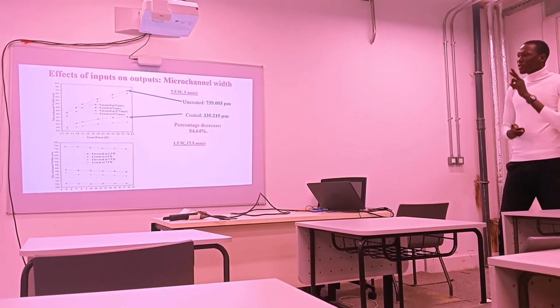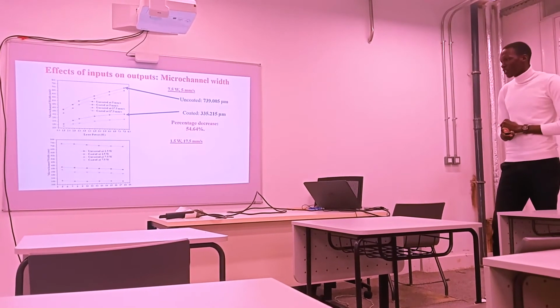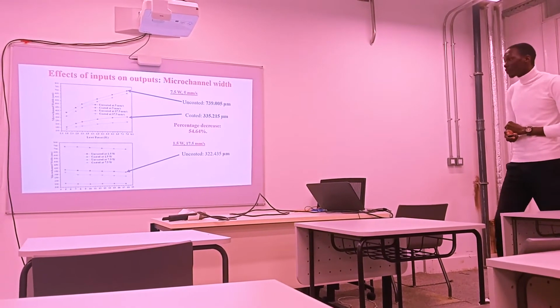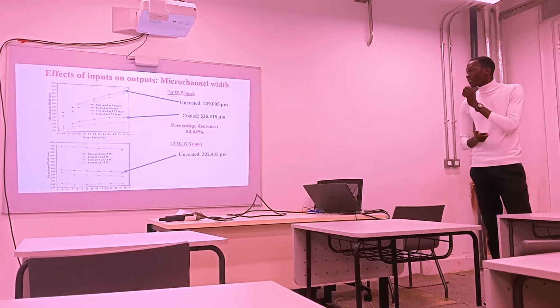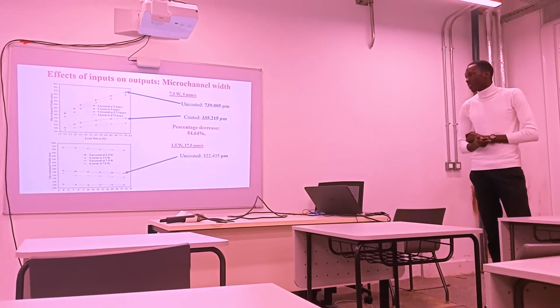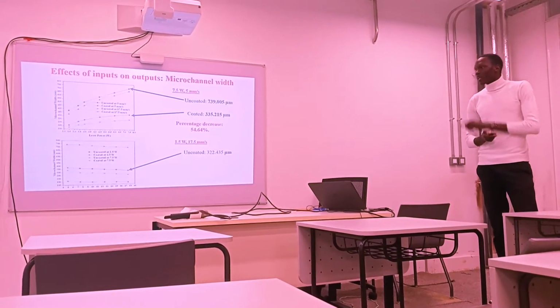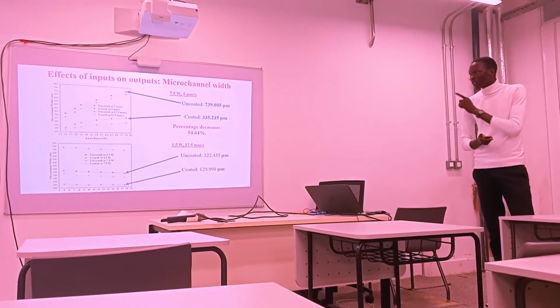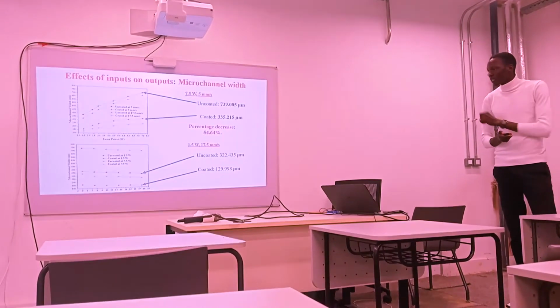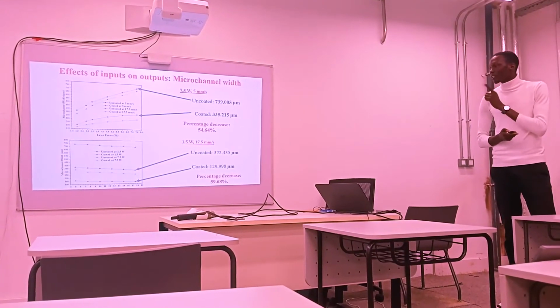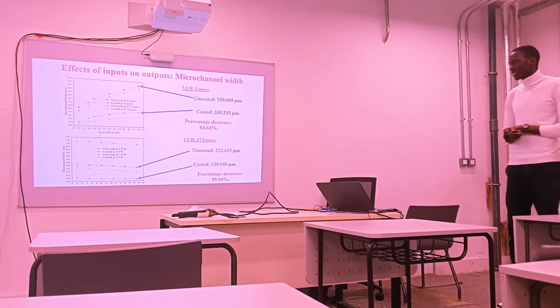Then, at the minimum power and maximum speed, for the uncoated, we got the value to be 322.435 micrometers. At the same condition, for the coated, we got 129.998 micrometers, a percentage decrease of 59.68%.